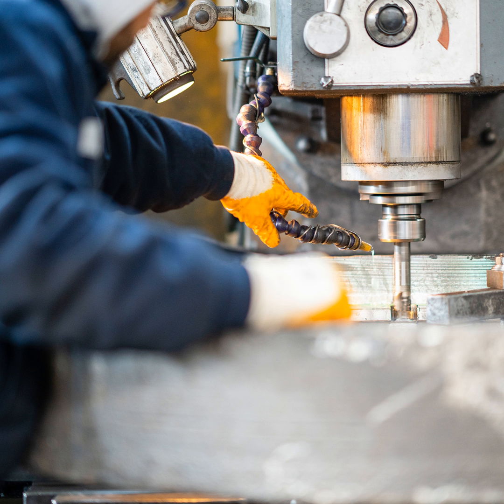Our famed dragon skin coating is a multi-level layer coating. It can go up to 2,000 layers of coating. When we're looking at total thickness, on the larger tools it's around 3 microns. But within that, there are many, many nano layers of each coating. This allows a feature called crack stopping structure, which prevents cracks from spreading throughout the cutting edge, which presents longer tool life to the cutter.